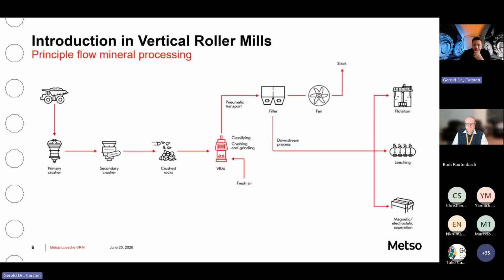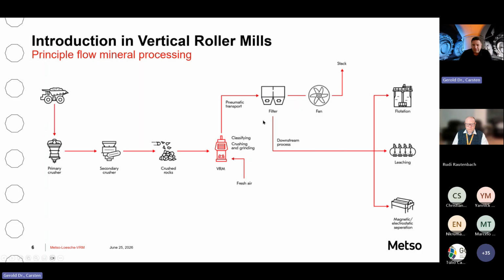Firstly, a general flow sheet, or a standard flow sheet, as I would call it: we have the primary crushing coming from the left, secondary crushing, and then we feed the Metso Loesche VRM. At the end of the process, we have a fan that is sucking air through the complete system. I'd like to recall it's a dry grinding principle. And the final product is dedusted in a baghouse. Usually the target is to produce a primary feed for primary flotation, for fine leaching, or for rougher magnetic separation.